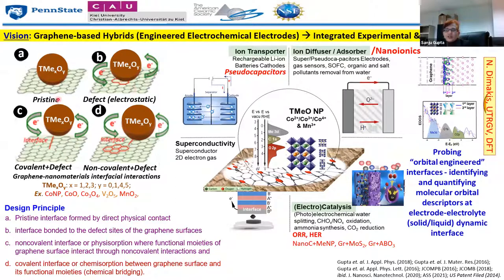So these are different interactions of the graphene with the other nanoparticles. Then it can be covalently attached, and that is the property that we have utilized by strategizing our synthesis processes. Or it can be a non-covalent interaction with the defect or these nanoparticles. Of course, everything, as I mentioned, is occurring at the interface. Here, in a way, we are using this conductive material, because we know graphene is conductive, and graphene oxide or reduced graphene oxide becomes our platform for studying this.